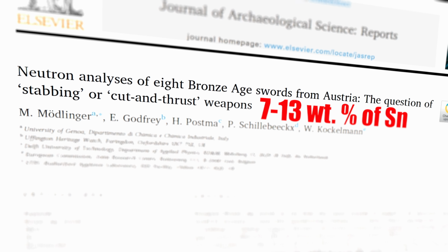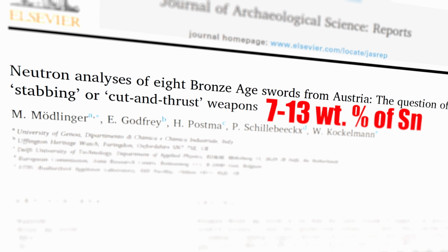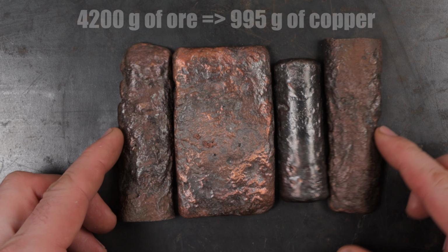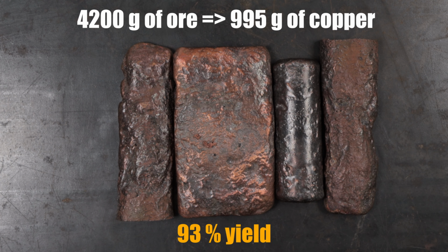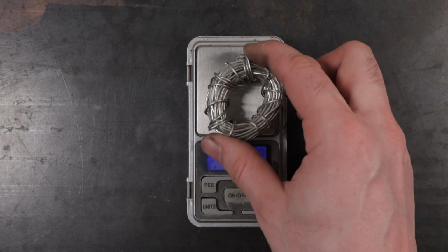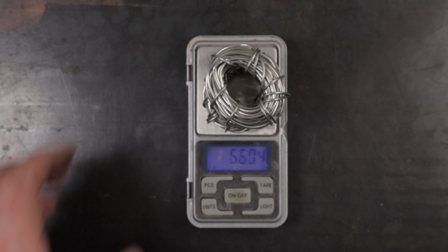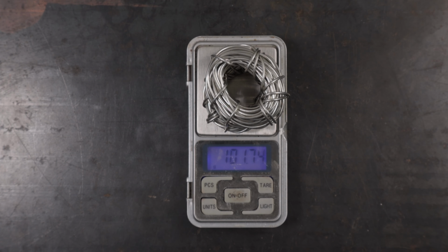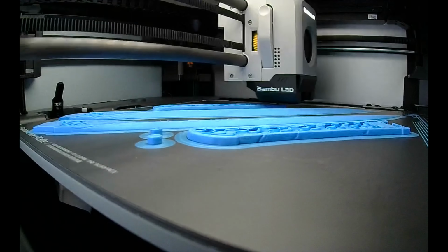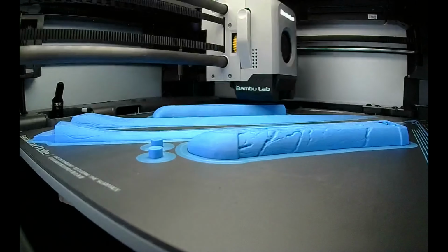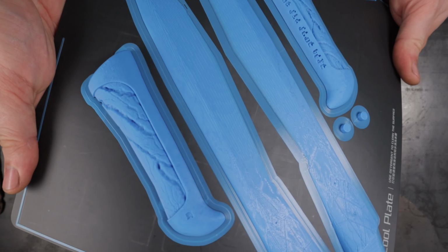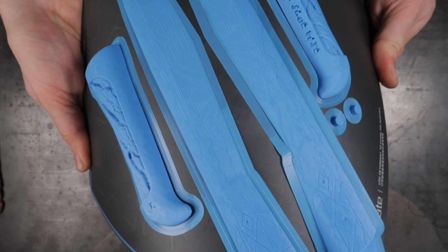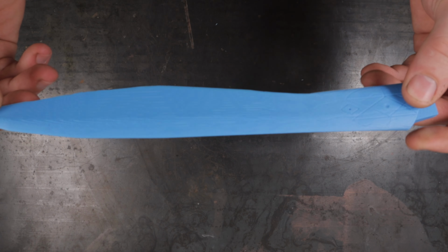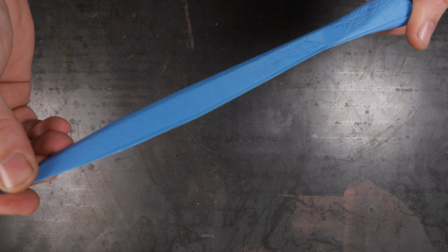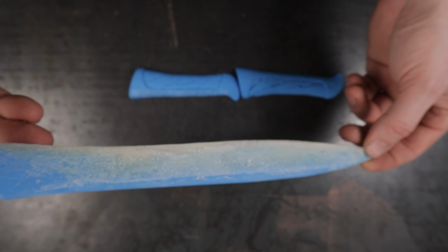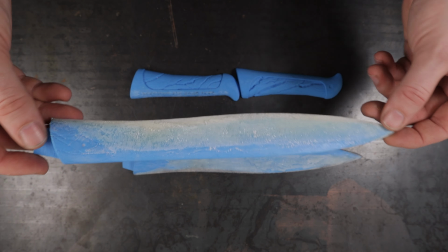I did my research and it appears that the Bronze Age swords had between 7 to 13% of tin. So for my amount of copper, I need approximately this amount of tin. But before I do the casting, I obviously need the model first. So I printed one of the available Crysknife models. I wasn't really happy with the shape of the blade, so I made a few adjustments.